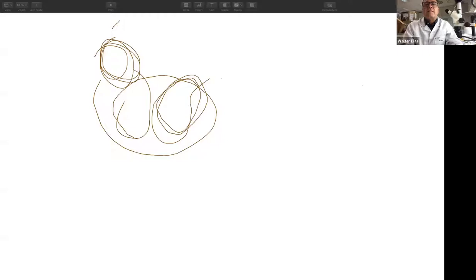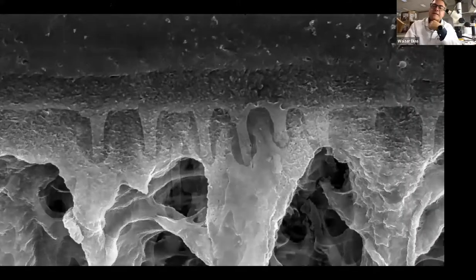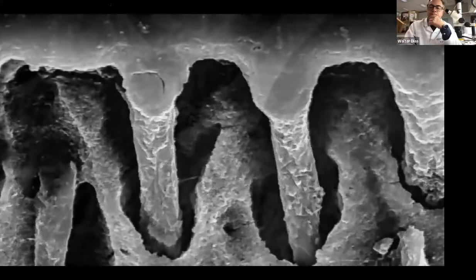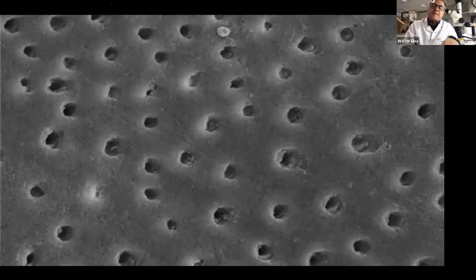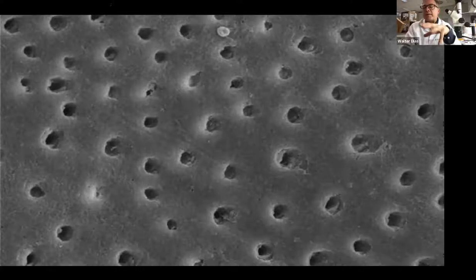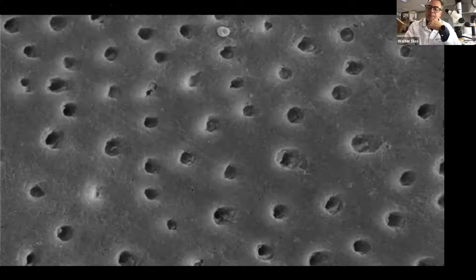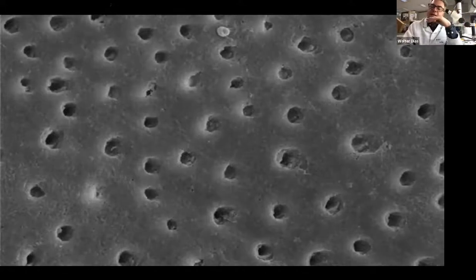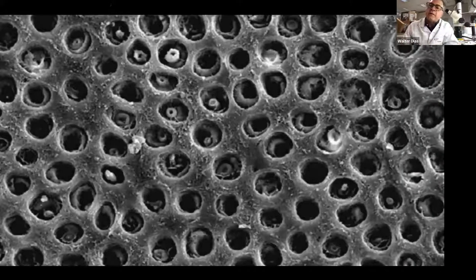Another thing we have to consider is the depth of the dentin that we're working with, okay? If you look at this case here, this is a case where you have the dentin at 1 millimeter from the DEJ. This case has a lot of intertubular dentin. It's very easy to work with, yeah? But if you etch this, especially if it's mid-dentin, then you have a completely different scenario. It's a completely different ballgame.